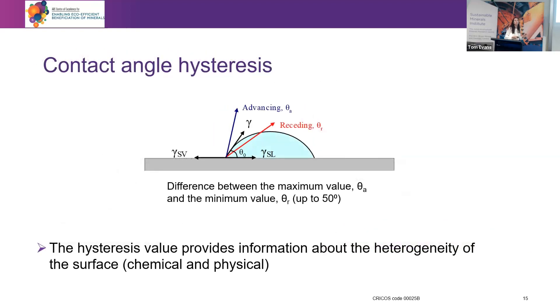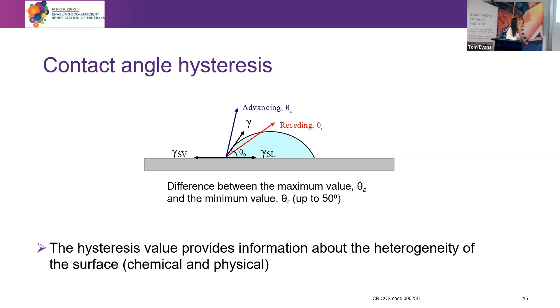Despite that, we are actually doing a good job at understanding what's going on on the surfaces. What I wanted to point out is that when you conduct advancing contact angles and receding contact angles — where the droplet or bubble recedes over the surface — the difference between these two values tells us something about the chemical heterogeneity of the surfaces. The higher the chemical heterogeneity, the larger will be the difference between the advancing and receding contact angles.